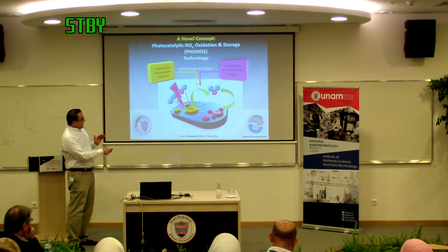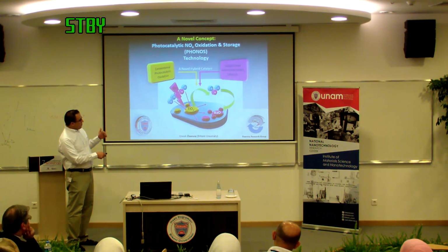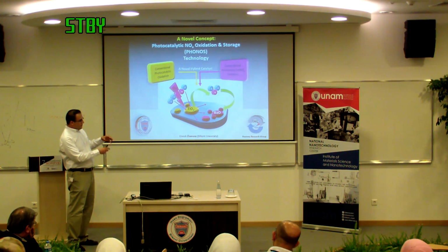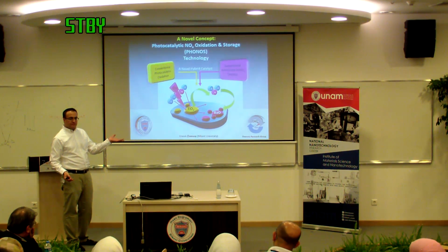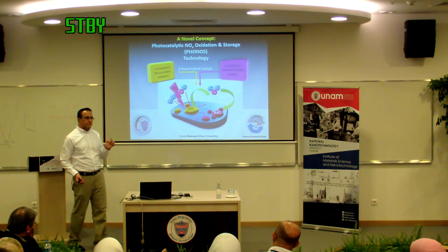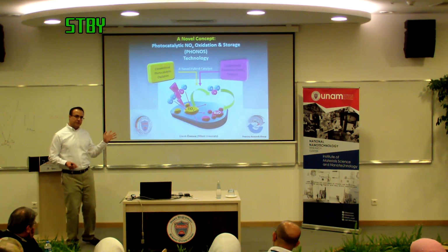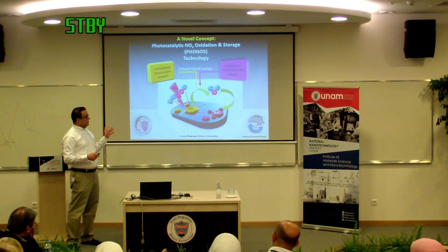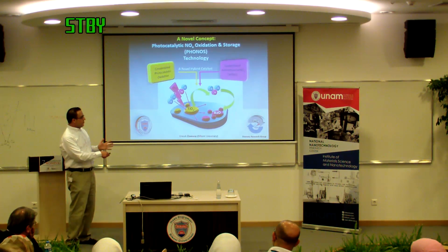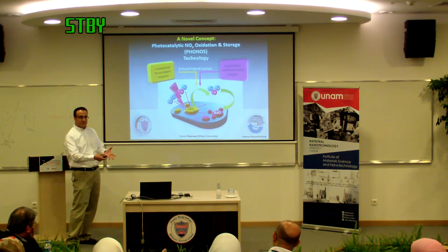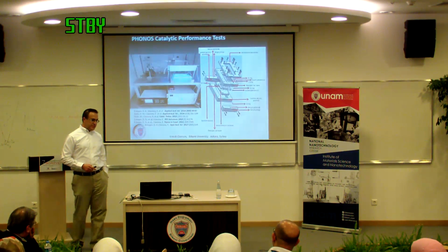If you can oxidize to NO2, then you can store it using basic nanoparticles like alkaline earth oxides, calcium oxide, magnesium oxide, in the form of nitrates and nitrites, and bingo, it will keep on sucking the NOx. Every now and then, if it rains, actually if it rains once a month, you're good, and I will show that it works for hours and days. This may not work in Qatar or in Egypt, in the desert. You need rain for regeneration, to get rid of the nitrate after saturation. But if you have some reasonable rain, this can work.